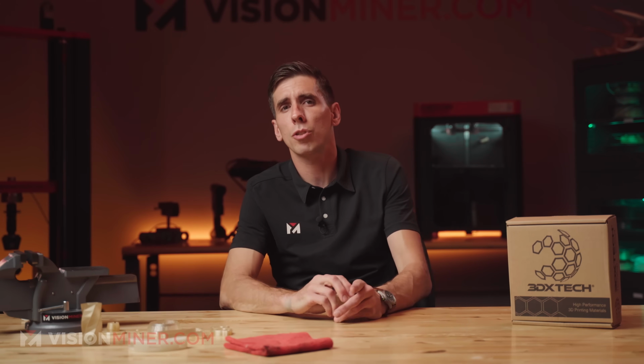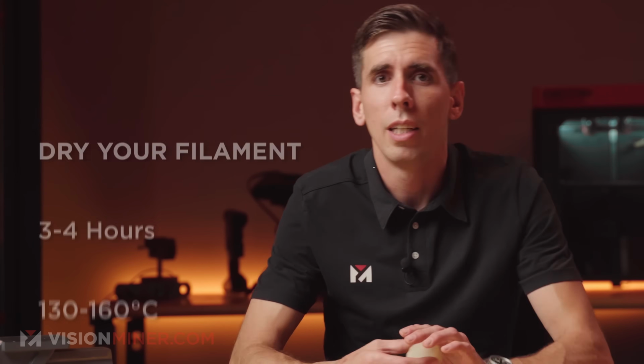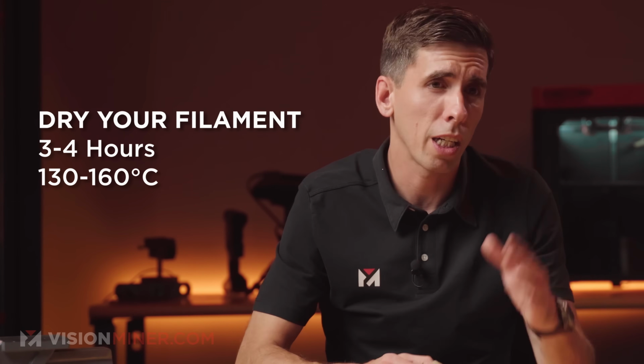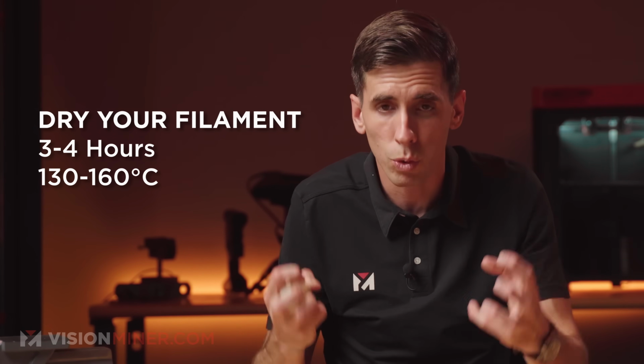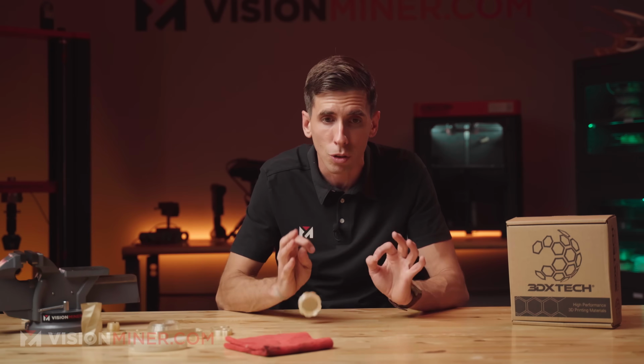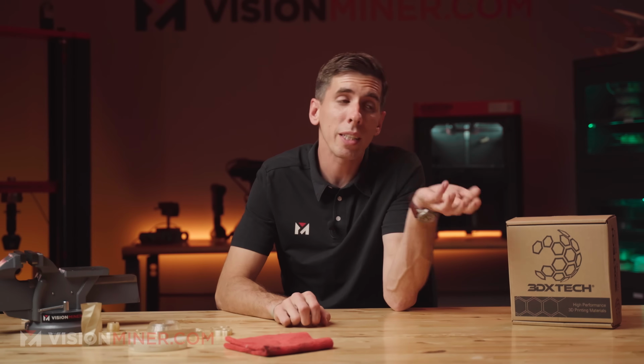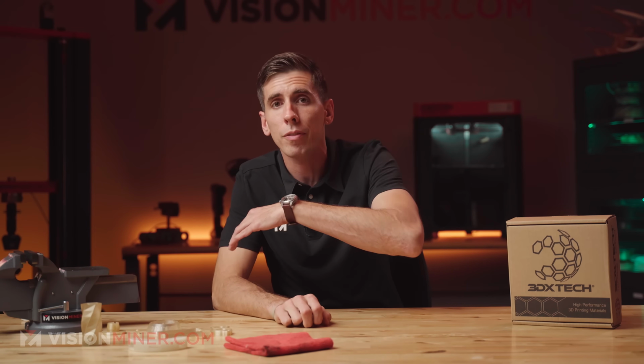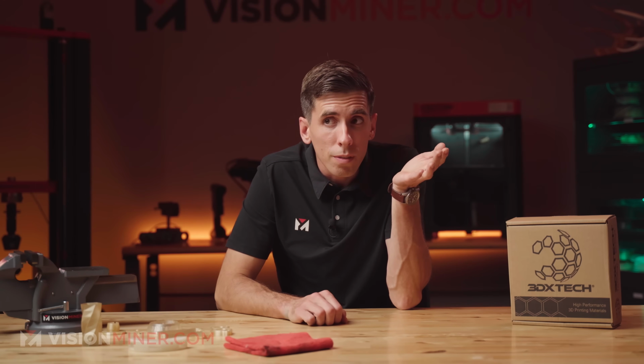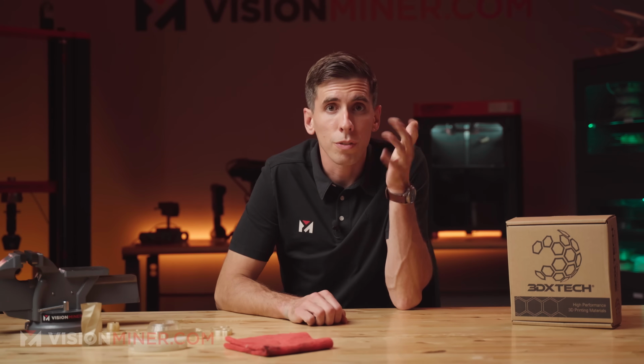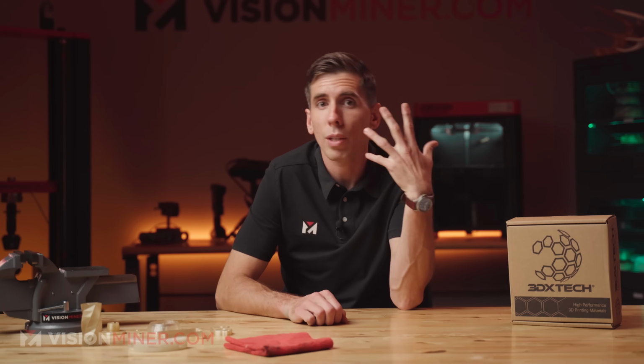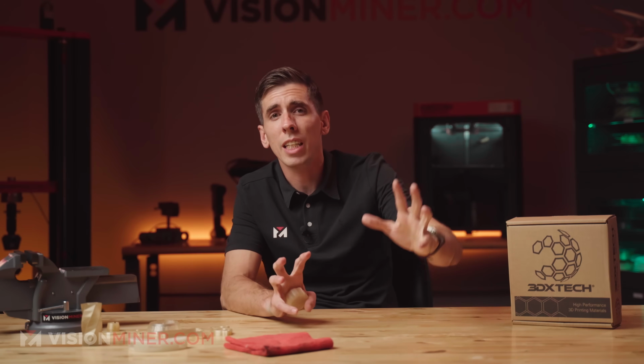The most important part, especially in the high temperature filaments, you must dry this filament. At least 3 to 4 hours between 130 to 160 Celsius to really get it dry. That is absolutely completely critical. Now ideally you can just leave it in a vacuum oven overnight at about 120 to 140 Celsius and you'll be totally fine. If you don't, PSU is very hygroscopic, so if you skip drying it, you're going to get steam bubbles, rough surfaces, and just generally ugly, weak prints.